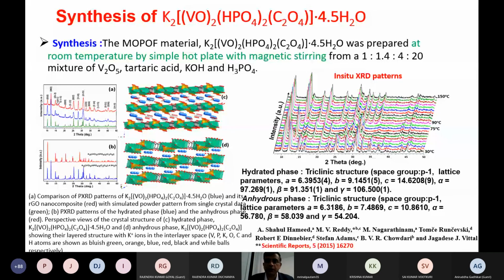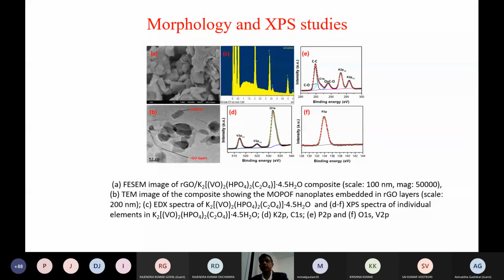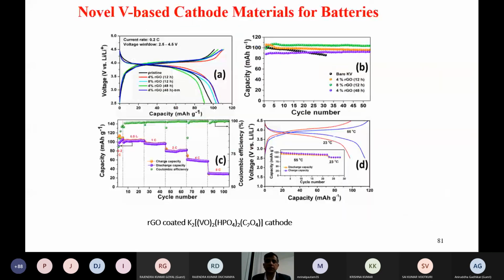And remember, we have to get rid of the water, because for batteries or any energy storage, we have to remove the water. We don't want water. So again, remember, minimum 150-degree heating is needed to get rid of the water, and we can get the new formula. We can characterize it by SEM, XPS. There are other physical studies people can do and see, for example, the presence of metal ions or the oxidation state, etc. And interestingly, as I told you, nearly 4 volts potential we can get, and around nearly 110 milliamps.